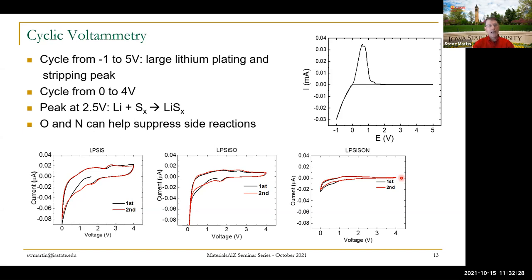And as we add oxygen, as we add nitrogen, we tend to clean up. Remember that defect site went way down? Maybe that's what's going on. We're kind of cleaning up the glass and eliminating that sulfur. Let's look at electrochemical impedance now.